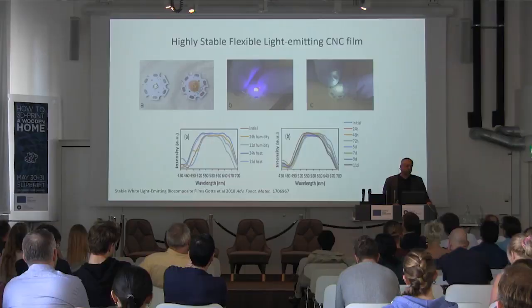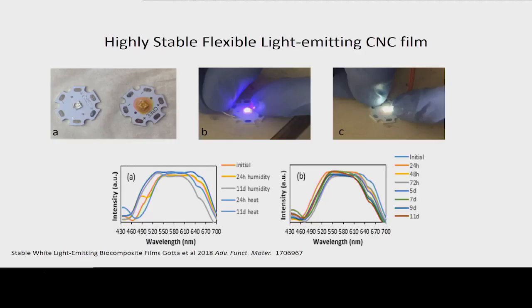More recently, we have shown with another group that we can now use these materials for LED lighting. You know that LED light, white LED light, is a result of use of filters that are made of rare earth elements and some very toxic materials. So we have shown that by mixing two organic pigments with the nanocellulose, we are able to form a very strong and quite effective coating to achieve a white LED that, as you can see at the bottom, is very, very stable, both at high temperature and in UV light.